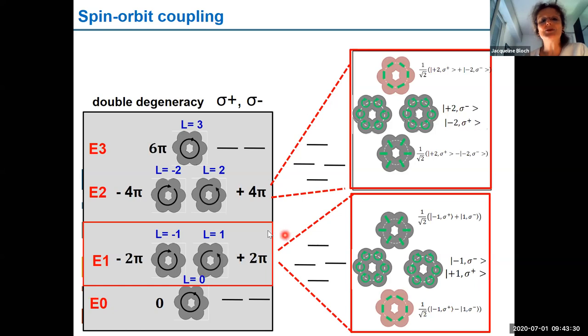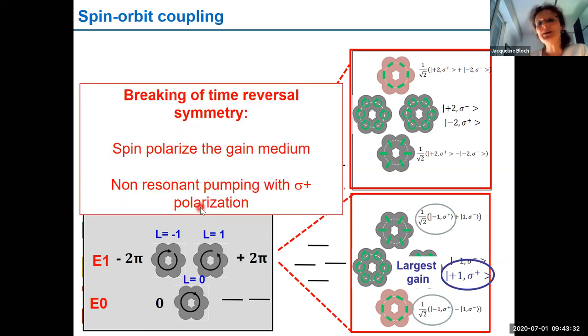And what is nice is that you can break time reversal symmetry by pumping the system with a circular polarization, so imposing a sigma plus polarization. What we are going to do is to pump non-resonantly. So we create high energy electron-hole pairs, which are spin polarized. They will relax emitting phonons. They will lose part of their spin polarization, but you will see that we will still have some remaining circular polarization of the gain medium.